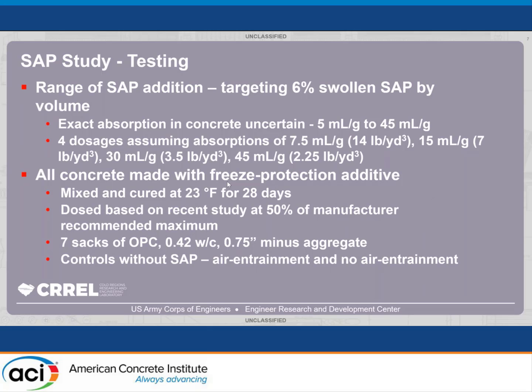So for testing, there's kind of a lot of words on this slide, but the basic thing we wanted to share with you guys is the range of SAP was something we kind of had to figure out with this. And we were targeting a 6% swollen SAP by volume, but the exact absorption is not really certain. And so it was estimated to be somewhere between 5 milliliters per gram to 45 milliliters per gram. And so for this test study, we tried 4 different dosages, assuming absorptions in that range, starting at 7.5, going to 15, 30, and then ending at 45 milliliters per gram. Again, that's because that absorption of the SAP is really not known. And so we had to test out all these different ranges.